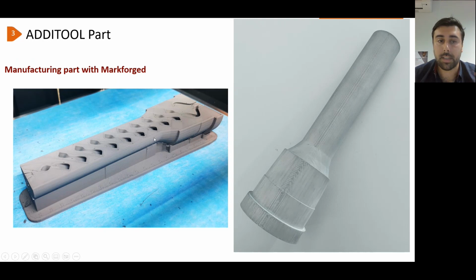So they print horizontally, and then they can push it into the oven horizontally. And you also see some support to avoid collapsing or deformation of the geometry with such a big part. And inside, this is a cutting. You have all the cooling channels near the periphery. So this is a part manufactured by Markforged with filament.